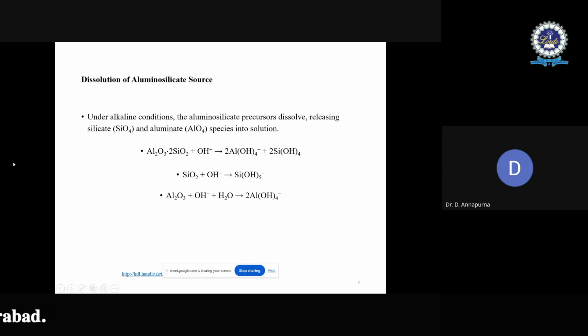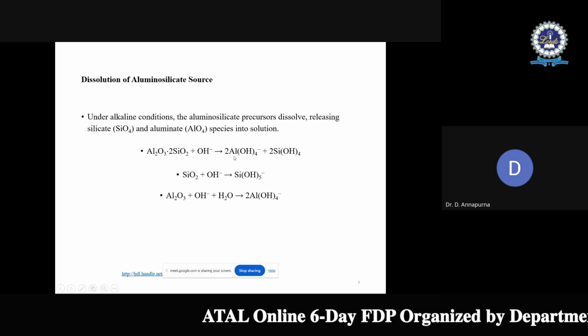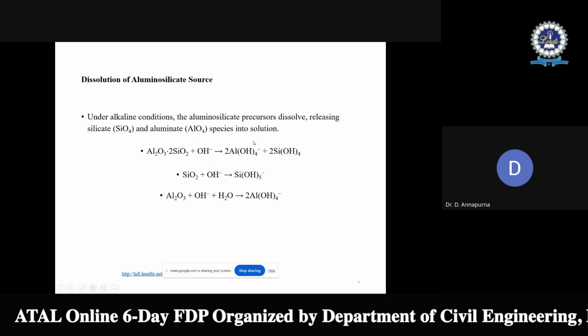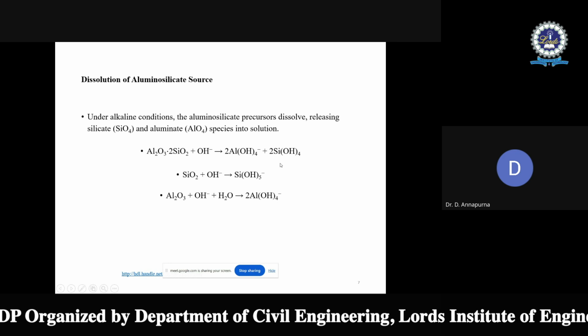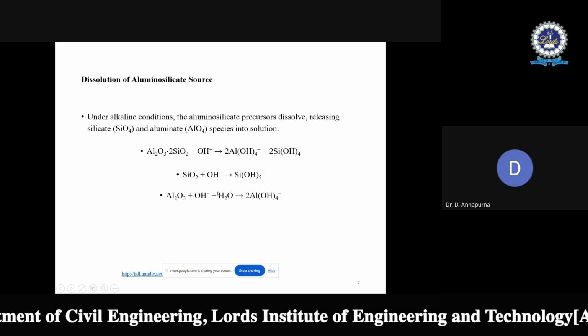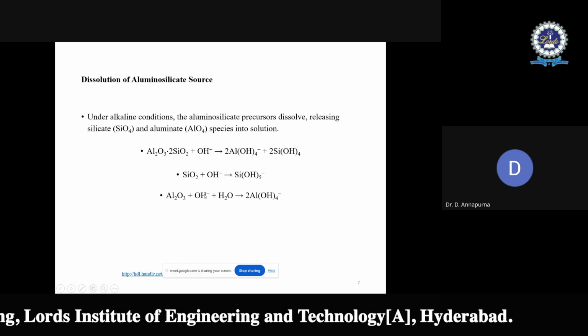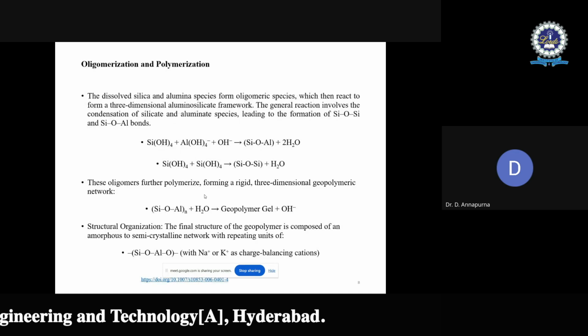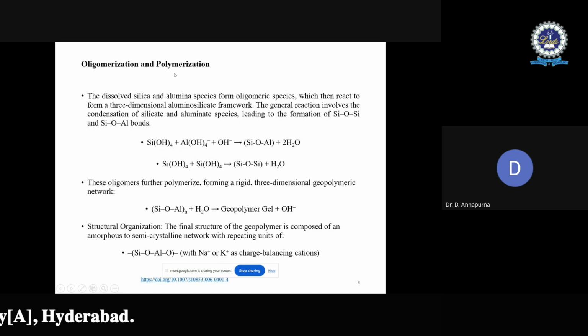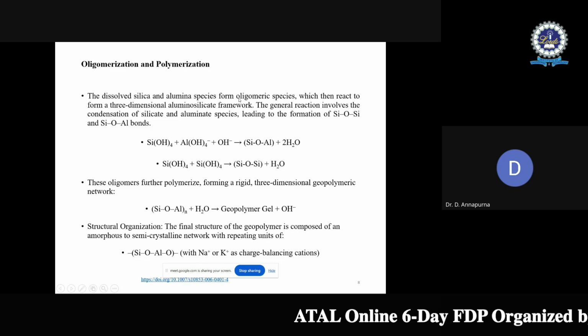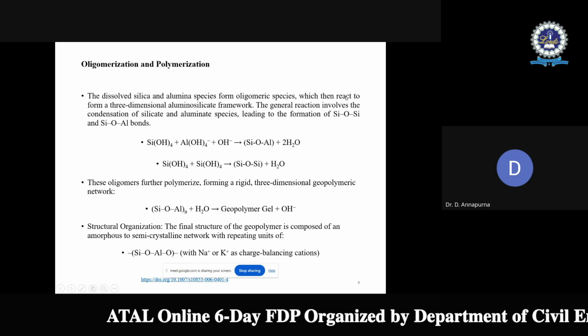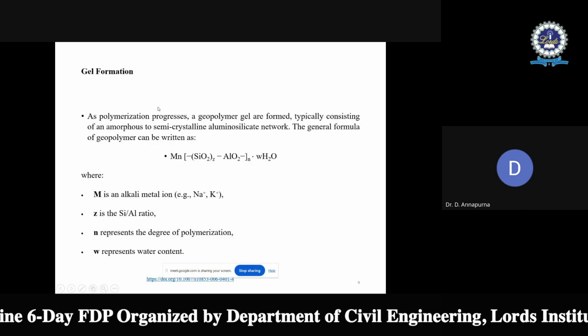So this is an aluminosilicate material, which is a precursor. Under this alkaline medium, it is going to dissolve and give two products, silicates and aluminates. Further, the silicate and aluminate will have an interreaction. So this is going to occur in the dissolution process. After dissolution, oligomerization and polymerization do occur. In the oligomerization process, the dissolved silica and alumina species form oligomeric species, which then react to form a three-dimensional structure.